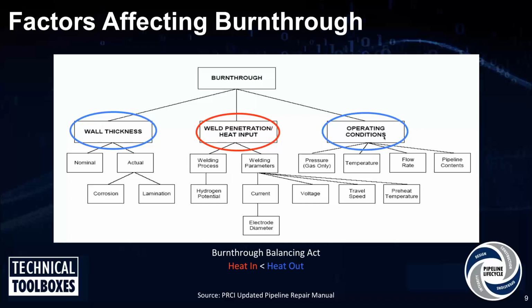And this is the same balancing act I'm going to talk about when we talk about hydrogen cracking, but from a different perspective. So from the burn through perspective, the balancing act is, hey, we don't want the pipe wall to get so hot that it loses its strength and we burn through. So what we want to do is make sure more heat leaves the weld region than goes into the weld region.